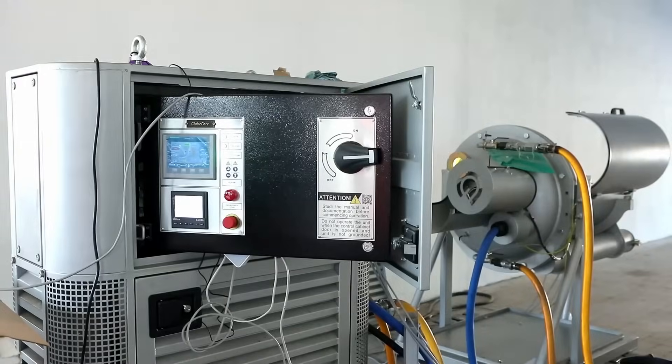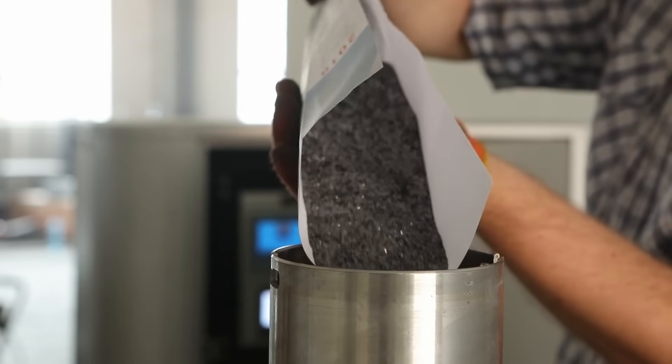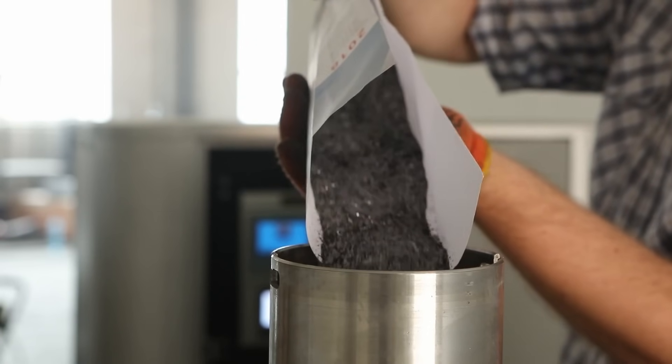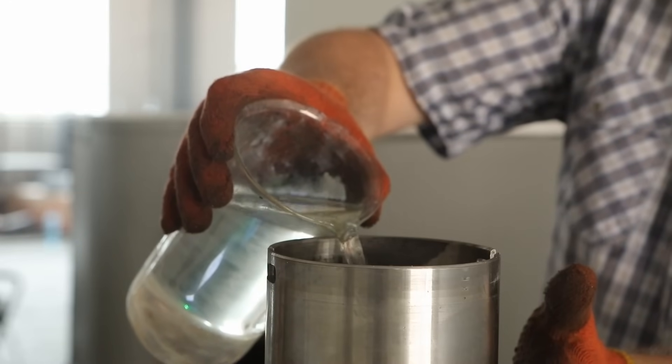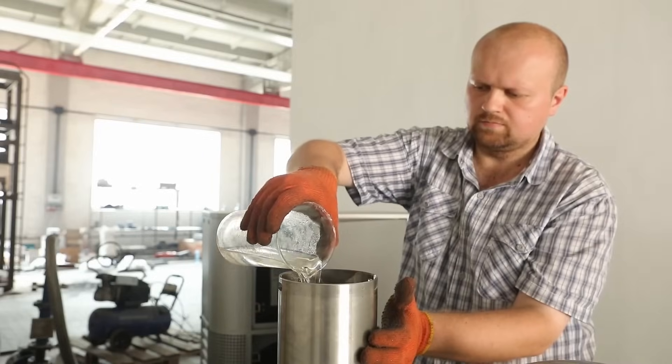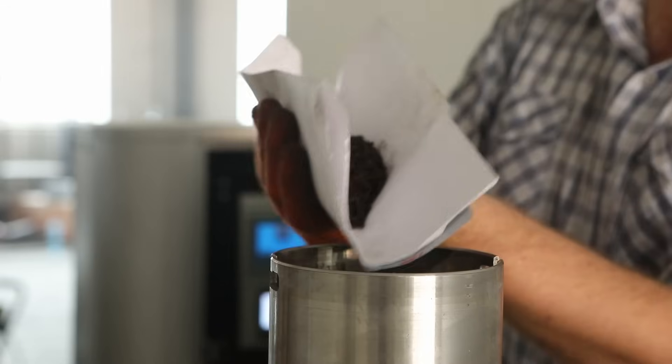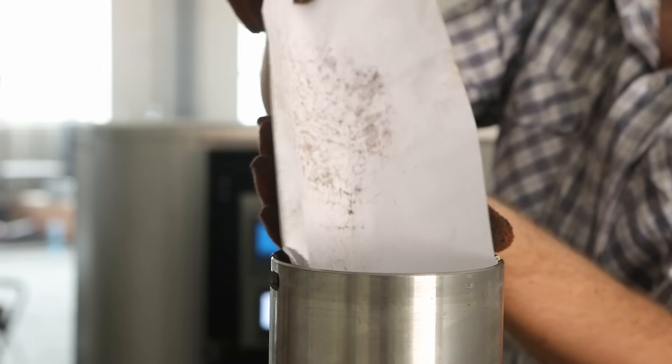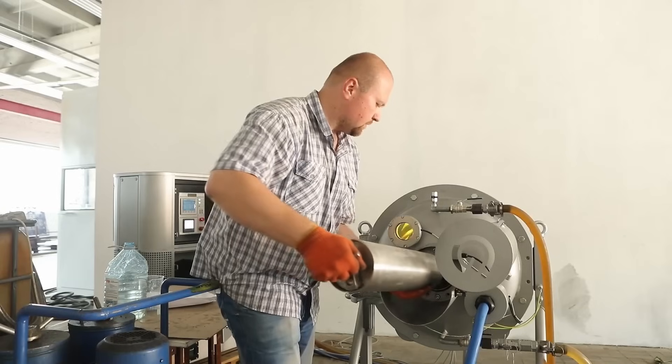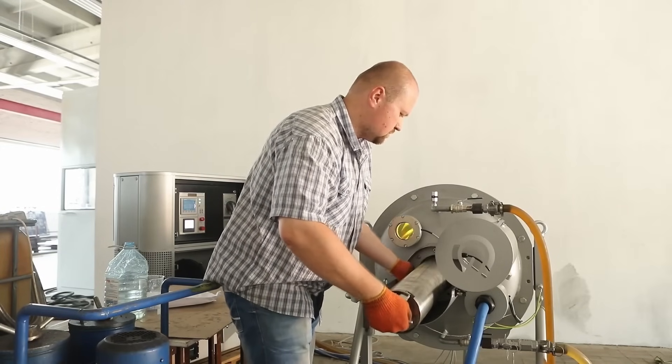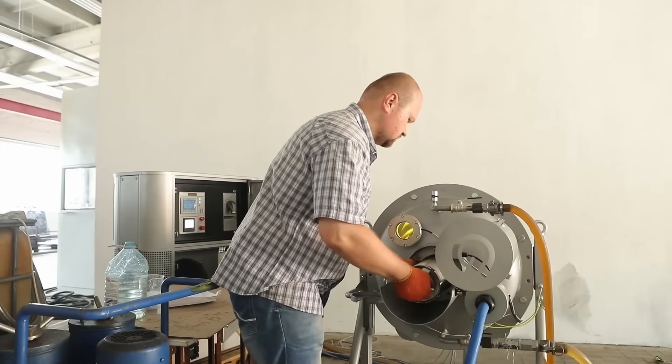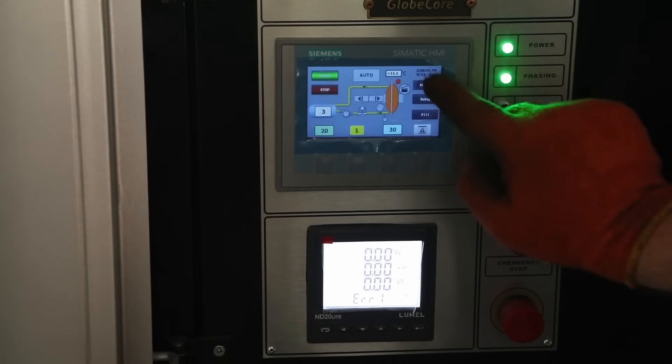First, we prepared 600 grams of graphite, 1.65 liters of distilled water and 500 grams of steel ferromagnetic particles with a length of 15 and a diameter of 1.5 millimeters. All of this was placed in the working chamber of the vortex layer device AVSP150 and was milled for 10 and 20 minutes.